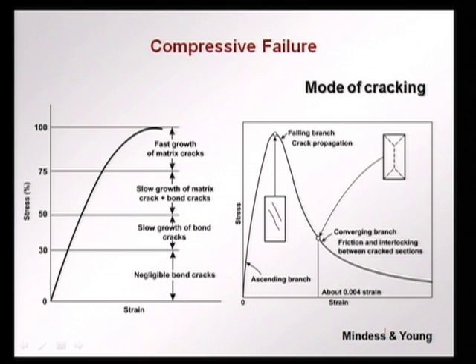When we do a test in the lab, we would find that at this point we would have some cracks in the specimen, and afterwards if we can control the test such that we have the softening branch obtained in a stable manner, we will see these cracks develop further, connect, and we have failure in the form of a cone at each end occurring. This is a cylinder which has been loaded in uniaxial compression, we would have the cones occurring at the top and the bottom, and we have some vertical cracking and disintegration of the concrete over the middle.